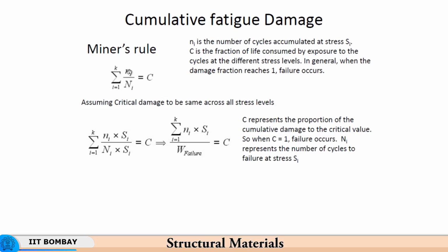Now, this quantity characterizes the cumulative damage in the system. As this quantity reaches a value of 1, then the damage is complete. So, if I have subjected this to 1000 cycles at stress Si, and the fatigue life at stress Si is, let us say, 10,000 cycles, then I have accumulated 10% damage during my 1000 cycle schedule as far as the fatigue damage accumulation goes.